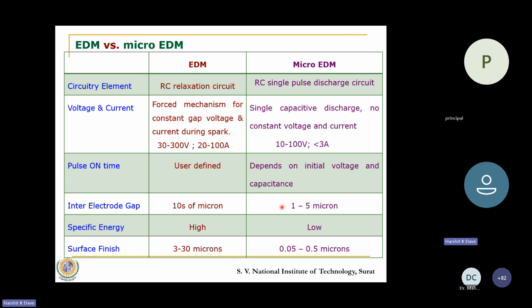So basically here you use the capability of a capacitor. How much energy a capacitor can discharge, you focus on that in an RC single pulse circuit. So rather than focusing on setting voltage or current, you focus on setting the capacitance. Of course, I will not go into too much detail, which may not be possible in this brief time. In EDM, the pulse on time is user defined. I can set the on time as 100 microseconds, 200, 500, or 50 microseconds. But in micro EDM, you don't set the pulse on time. Of course, some machines give you an idea of how much the pulse on time would be. But depending on the initial voltage and the capacitance, a certain pulse on time is defined by itself. So you lose one parameter as a variable for study.